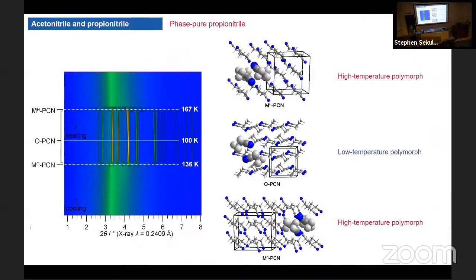Propionitrile behaves a little bit more logically under our conditions. When we are cooling down, we have the high temperature phase crystallizing as expected. Then we have the phase transformation to the low temperature form. And once it's heating up, we have again the high temperature form. This one was solved and we were scooped, but these two were not solved. We solved them and we are looking forward to publishing all of this data together.